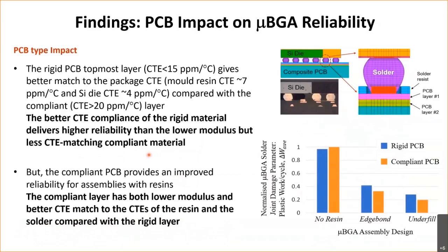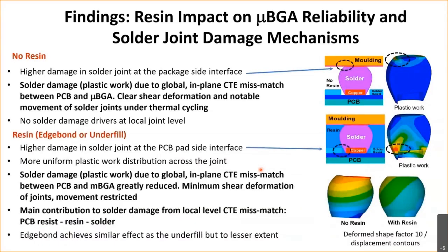In essence, the findings here for looking at a rigid board or this compliant board: not a great difference, due to a number of reasons here, but you do need a resin as well, whether it's a rigid or a compliant board. Here we can see when no resin is used that the damage or the crack will initiate at the top of the joint. When we use an edge bond or an underfill, the damage moves to the other side of the joint. But generally here, the edge bond or the underfill with a micro BGA is very beneficial to solder joint reliability.